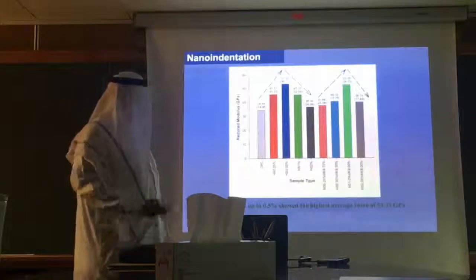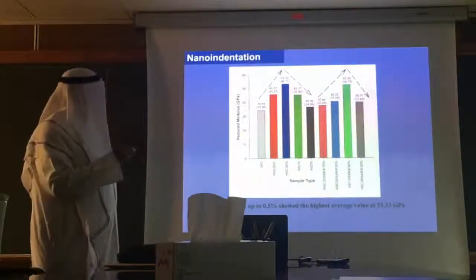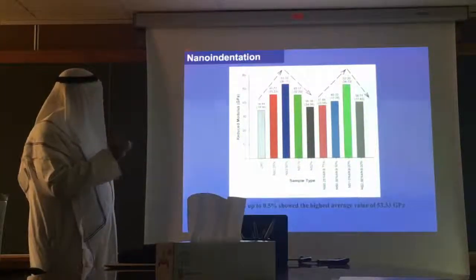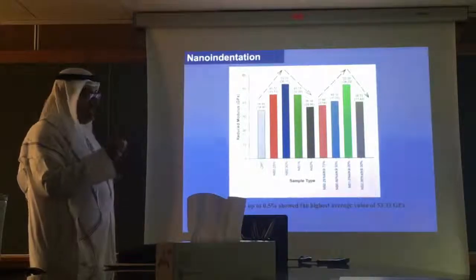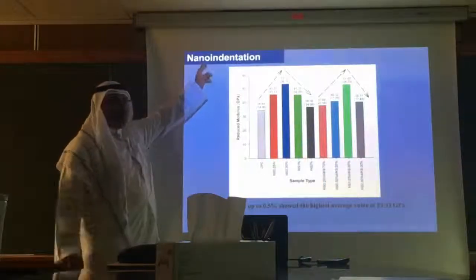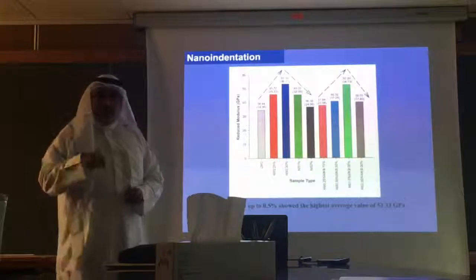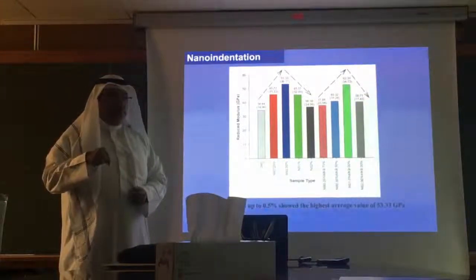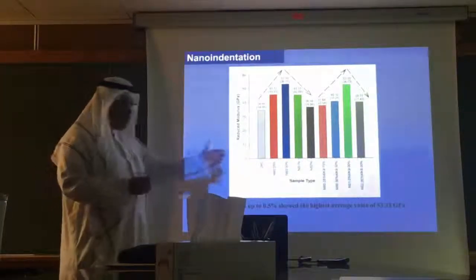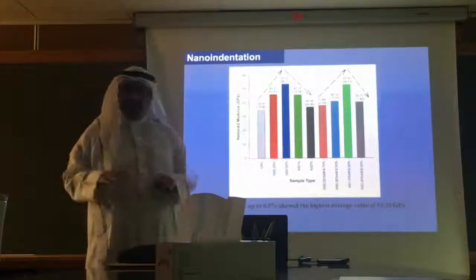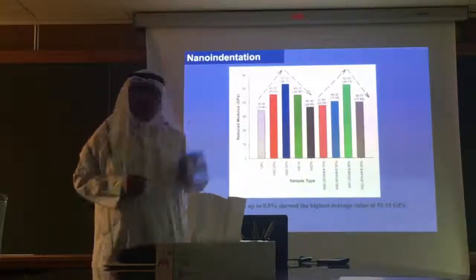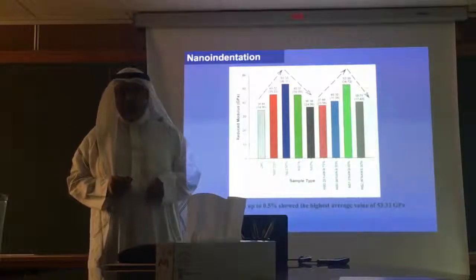I'll show you just one quick result. This is the reduced modulus. We did this in the College of Engineering here. We have nano-indentation. This is one of the very important techniques for studying the mechanical properties of nanomaterials. But it has to be a very smooth surface. So we took our sample and we polished it very carefully to make it very smooth, and then we studied its mechanical property.